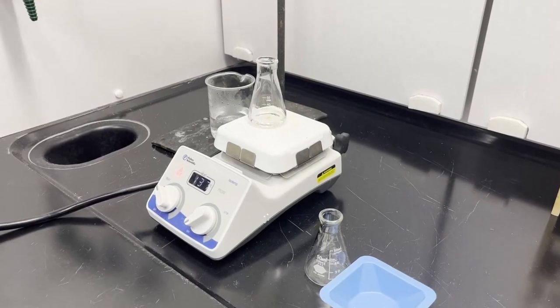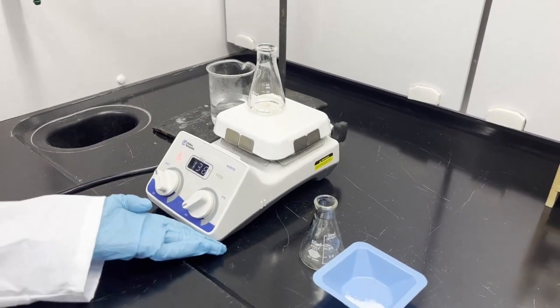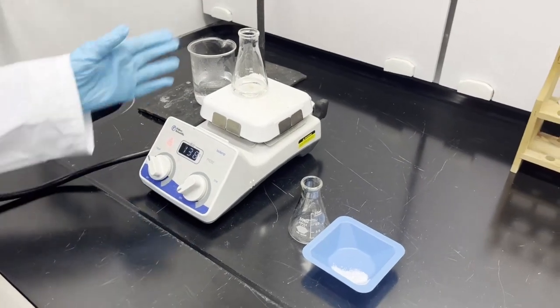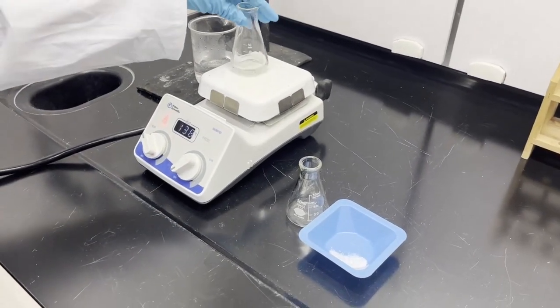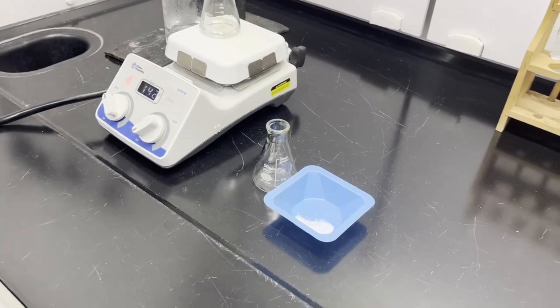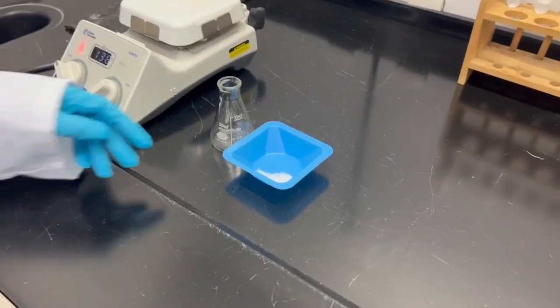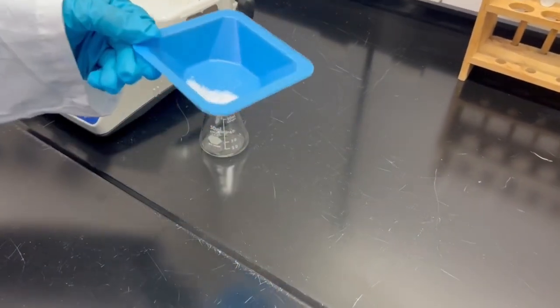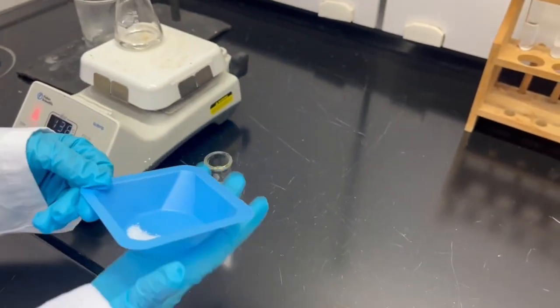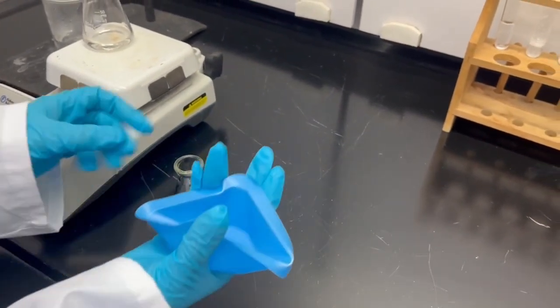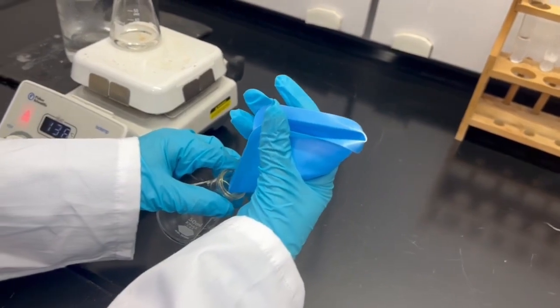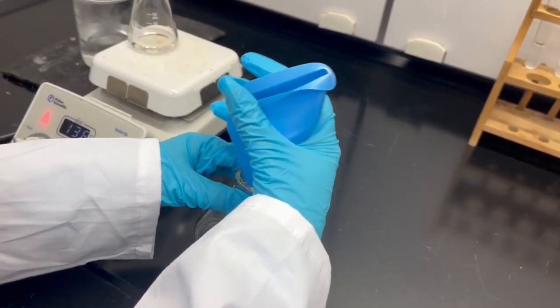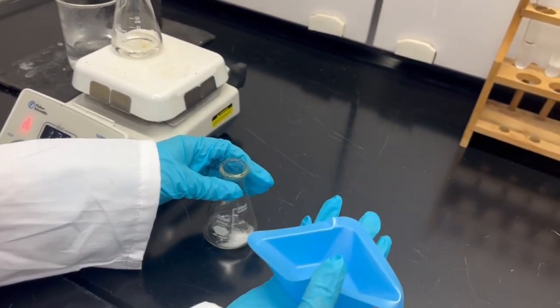Now start by heating your solvent in an Erlenmeyer flask on the hot plate. Heat till boiling or until you see condensation beginning to build up along the walls of the flask. While your solvent is heating, place all of your compound into a separate Erlenmeyer flask and add a boiling stone. For the next step, it's very important that the solvent stays hot so that your compound doesn't begin to crystallize before you can complete recrystallization.